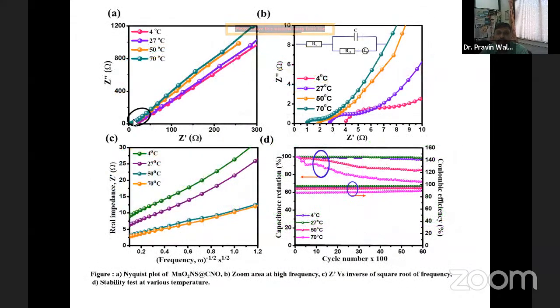Here you see how the conductivity is increased with respect to temperature. We have done temperature dependent measurements and can find the enhancement with increasing temperature. The capacitance value is increased, but at the same time you have to compromise your stability.